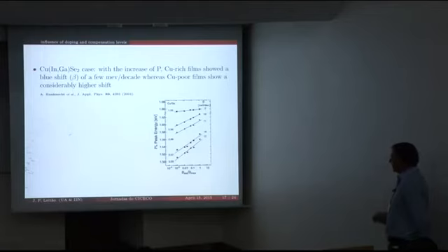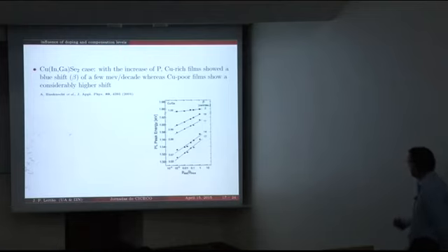Also, in this case, for CIGS, we see that if we have copper-rich films, as shown here, for example, the value of beta is very low, but when we start seeing copper-poor films, we start observing that these values of beta clearly increase.